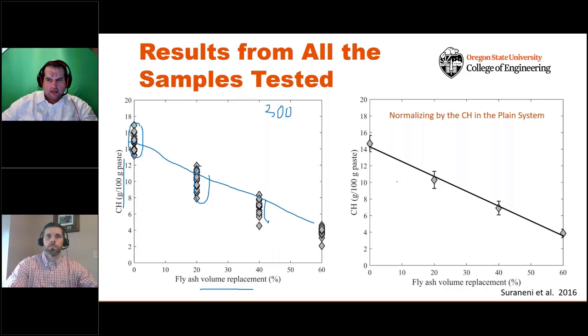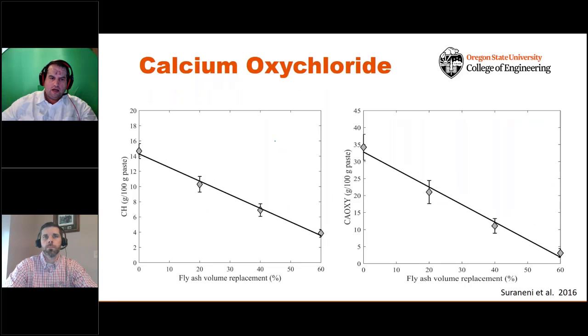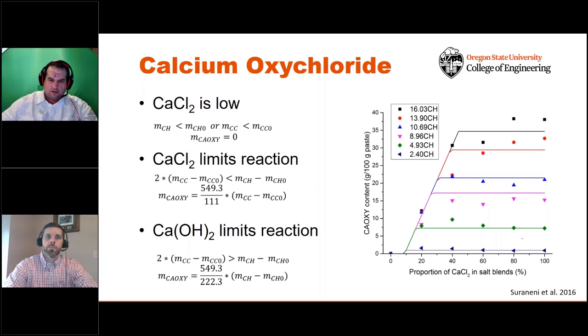Now, on the graph on the right-hand side, you may look at this and say, oh, those are nice little error bars. These aren't error bars. These are a collection of all the data if we normalize by the original amount of calcium hydroxide in the original system. So if we essentially say, how much calcium hydroxide did you originally have and how much does it decrease? What we see is a very, very consistent trend. More fly ash is better, more slag is better. Silica fume would be great, except it's hard to get into a pavement without causing other issues. Clays can be very useful if they're calcined in these systems. As expected, calcium hydroxide decreases. When calcium hydroxide decreases, calcium oxychloride also decreases in a very similar fashion.